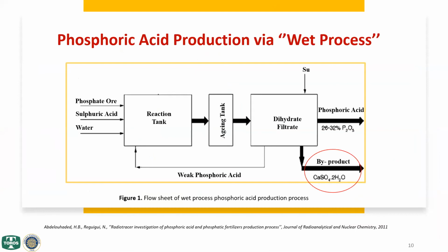So let me continue with phosphoric acid production. Phosphogypsum is a byproduct of the phosphoric acid production process, and more than 90% of phosphoric acid is produced via the wet process, in which the phosphate rock is dissolved in sulfuric acid. Although the wet process is economically feasible, its major disadvantage is the generation of large amounts of phosphogypsum.